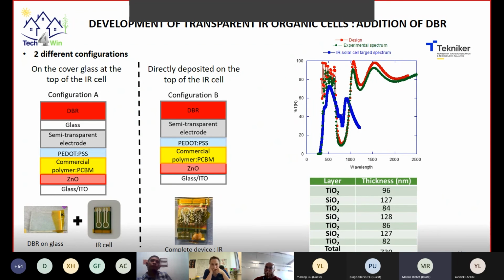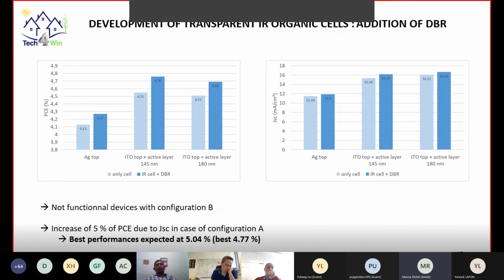So we test 2 different configurations to integrate the distributed Bragg reflector. The first one, configuration A, the DBR is deposited on glass, and this glass is just put on the top of infrared cells. And the second configuration, configuration B, consists of depositing the DBR directly on the top of organic solar cells. If we look at the results, there are no functional devices with configuration B, but with configuration A, we can see an increase of 5% of efficiency due to the increase of JSC. So we can expect performances at 5% if we consider the best organic solar cells at 4.77%.